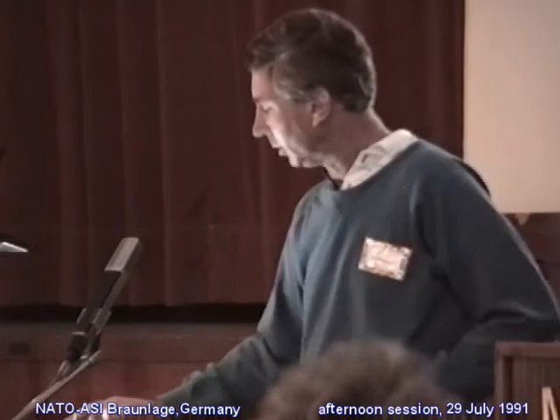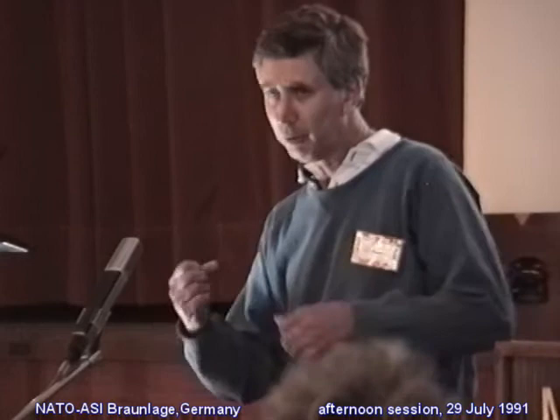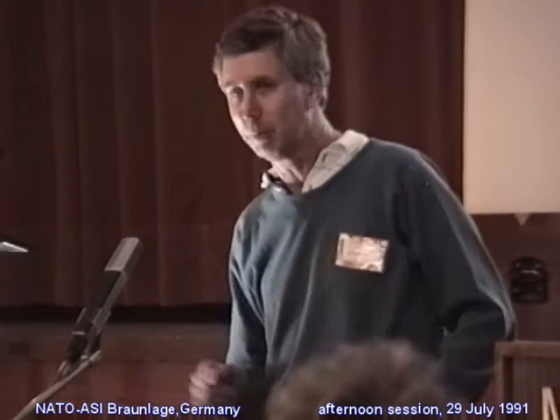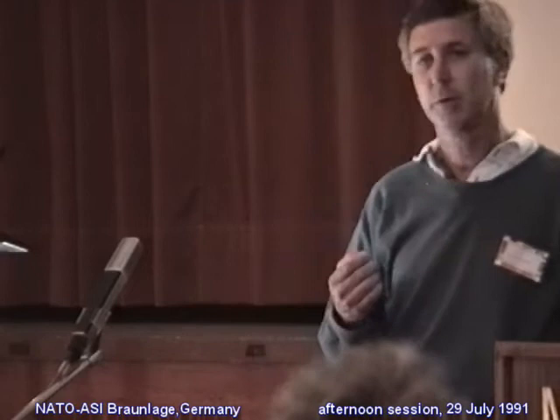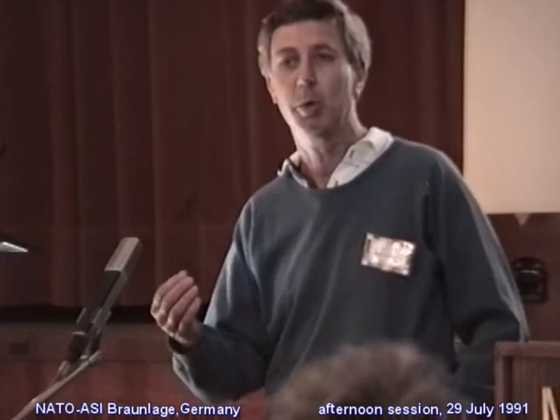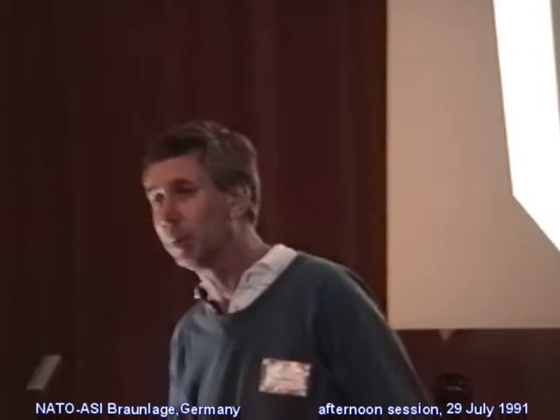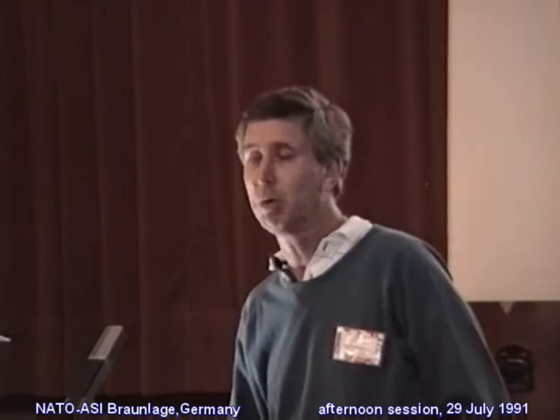And if you can now disturb that system from the state of equilibrium by increasing the applied load, then you start to increase the rate at which you can overcome the thermal fluctuations or overcome the energy barriers, and the crack will start to move forward at a certain rate or a certain velocity. And he re-derives Griffith's condition for fracture. Whereas we think of it as G equals 2 gamma, where G is the mechanical energy release rate, the kind of thing that Daniel Maugis expresses in his papers, he tends to write down a more fundamental equation for crack propagation in terms of G minus 2 gamma times the crack velocity.